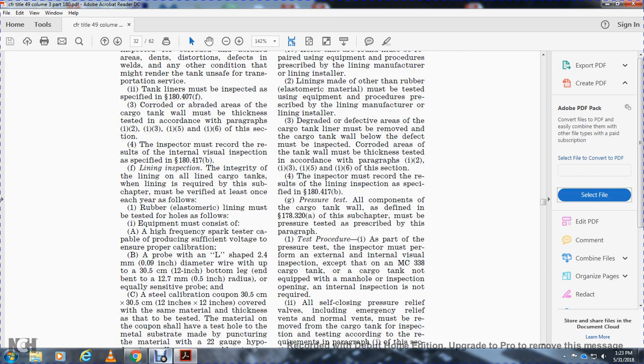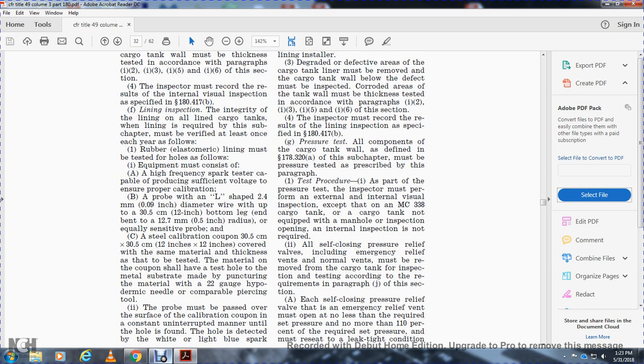Rubber or elastomeric linings must be tested for holes as follows. The equipment must consist of a high-frequency spark tester capable of producing sufficient voltage, with proper calibration. A probe with an L shape, made of 2.4 millimeter diameter wire with a 30.5 centimeter bottom leg, or 12 inches, bent with a half-inch radius, and an equally sensitive probe. Use a steel calibration coupon of 12 inches by 12 inches, covered with the same material and of the same thickness as the lining that has been tested. The coupon shall have a test hole through to the metal substrate, made by puncturing the material with a 22 gauge hypodermic needle or a comparable piercing tool.